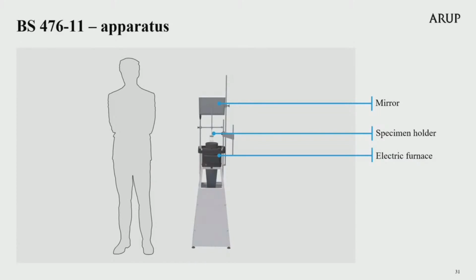The test apparatus in this heat emission test is similar to that used in the non-combustibility test, with a notable exception being the design of the specimen holder. Other amendments include a prescribed design for the electrical furnace windings. A mirror is proposed to allow the operator to observe flaming easier. The apparatus also includes an additional support to the specimen insertion device.